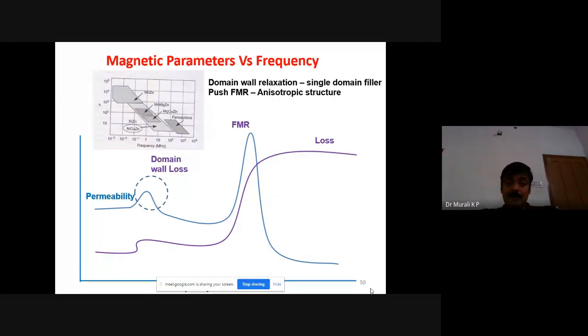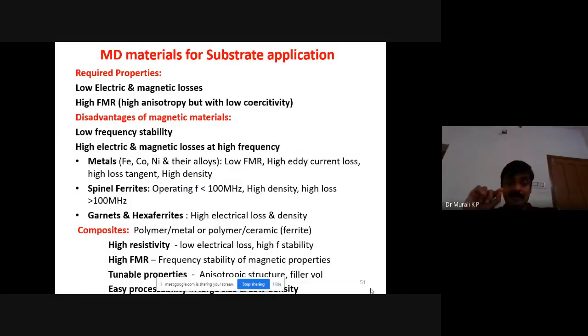So the materials for substrate applications should have low electric and magnetic loss and high FMR. The disadvantages of different materials are: if you take metal, it will have low FMR, high eddy current loss, high loss tangent, and high density. If you go for spinel ferrites, nickel zinc ferrite or something like that, it will have operating frequency less than 100 megahertz, high density and high loss above 100 megahertz. So it can be used below that range only, in the very few megahertz range.